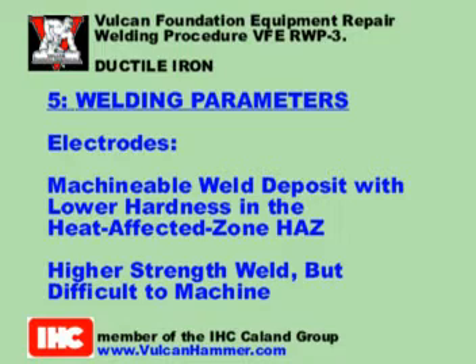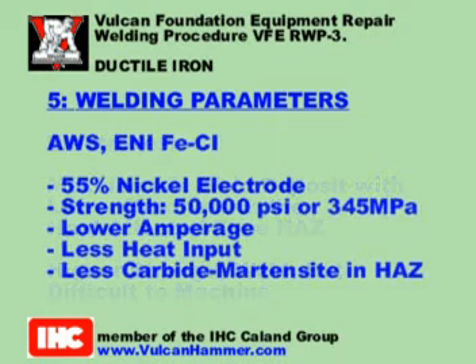Electrodes. 2 electrodes are recommended. The first produces a machinable weld deposit and a lower hardness in the heat-affected zone HAZ. The second electrode produces a higher strength weld but may be difficult to machine. Greater care is also required in welding with the second electrode to prevent cracking in the fusion zone.